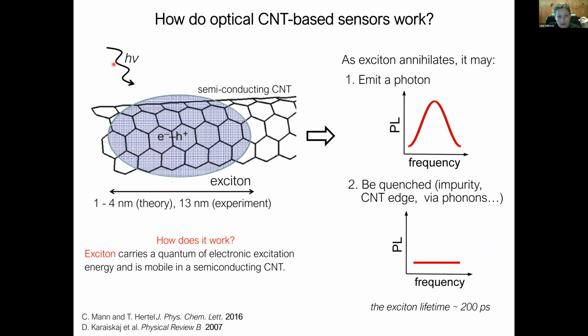It's based on the nanotube. When it absorbs light in a spectroscopy experiment, it forms a state called an exciton state. It's a state where you have a negatively charged electron and a positively charged hole coupled to each other and diffusing through the nanotube surface. So we were thinking, okay, if you create an exciton state, an electron and a hole, then this exciton should be interacting with the nanotube environment, with these rings, right?